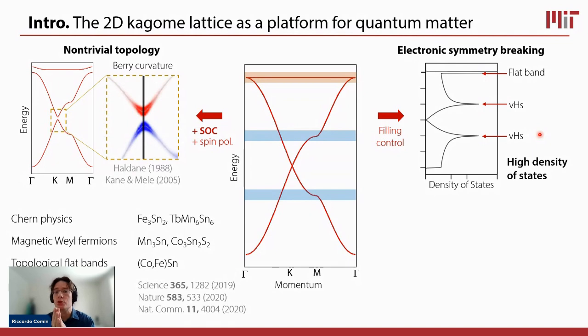And what we will tend to do is it will tend to break some symmetries in order to remove that degeneracy. So breaking symmetries, opening up a gap, splitting away the regions of high density of states and leaving a lower density of states at the Fermi energy through a mechanism which overall lowers the total energy of the system. So it's energetically convenient for the system to do so.